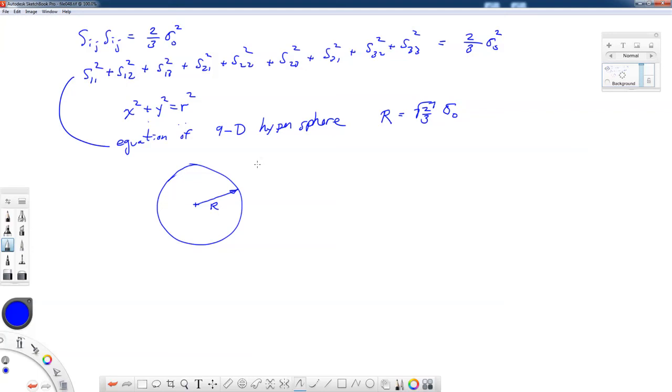Now, what makes this very nice for us to deal with is that we can show that we can use this surface as a plastic potential, and normal vectors to this surface are related to the directions of our plastic strain increments. And we can do lots of other interesting things. And we've reduced this very complicated problem to basically a solid geometry problem. Alright, so we'll get into that more as I continue these videos.